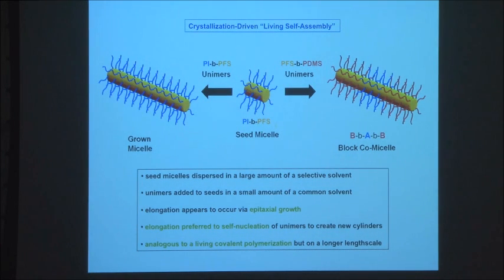But this process is very slow. This is a homogeneous nucleation process, whereas this seeded growth is kinetically much faster. And so we don't generate any new cylinders in this process. So all of the unimers you add go to the pre-existing seeds. So in many ways, this is like a living covalent polymerization, which I illustrated earlier, for actually making the block copolymers in the first place. This is just on a totally different length scale.